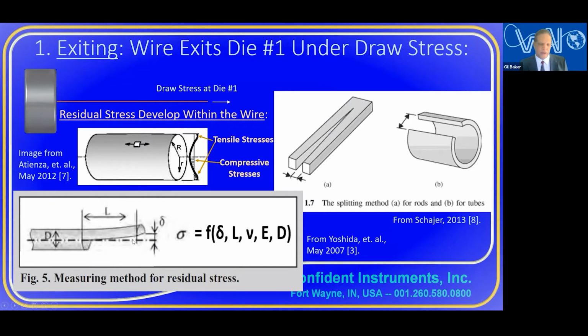They slit a very fine wire, and I guess they must have used the wire EDM both to slit it and cut off that bottom part, unlike here. Again, they're looking at the deflection of the cut part, half the wire, and then using that deflection plus the length of the slitting, the diameter of the wire, also Poisson's ratio and the elastic modulus, they're roughly approximating the residual stresses in the wire. Of course, they use more complex equipment, but this is just a check.